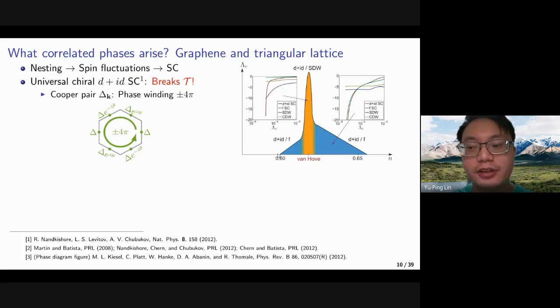So here is a phase diagram which could be applicable for graphene and the triangular lattice. If we look at the Van Hove singularity, we can look at the scale of the phase diagram, which is analogous to the critical temperature. We'll see that near the Van Hove singularity, there is a competition between the chiral d plus id superconductivity and the charge density, spin density wave. And away from it, there will be some other superconductivity. It turns out that under a renormalization group analysis that Rahul did in 2012, the chiral superconductivity will be the universal leading instability. And because it is chiral, it breaks the time reversal symmetry.